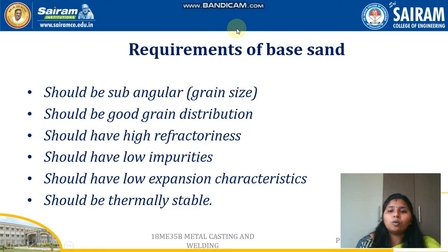Now let us see the requirements of a base sand. The grain shape should be subangular. It should have a good grain distribution. It should have high refractoriness, low impurities, low expansion characteristics, and it should be thermally stable. These are some of the requirements of a base sand.